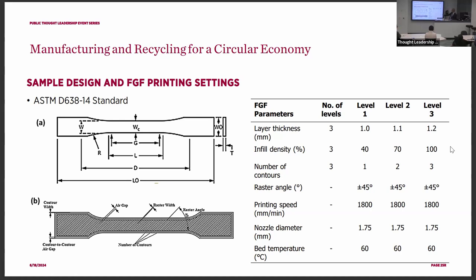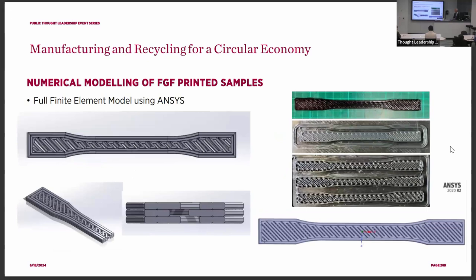For the raster angle, we didn't make a change. It's just positive, negative 45 degrees. And the printing speed is very fast, 1.8 meters per minute, very fast. And we use the same settings for the nozzle diameter and also temperature. So we're printing the samples.